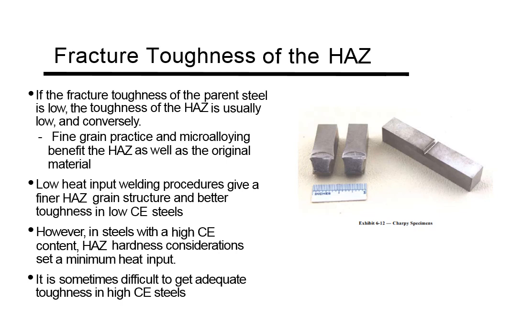If the fracture toughness of the parent steel is low, the toughness of the HAZ is usually low, and conversely, fine grain practice and microalloying benefit the HAZ as well as the original material. Low heat input welding procedures give a finer HAZ grain structure and better toughness in low carbon equivalent steels. However, in steels with a high carbon equivalent content, HAZ hardness considerations set a minimum heat input. It is sometimes difficult to get adequate toughness in high carbon equivalent steels.